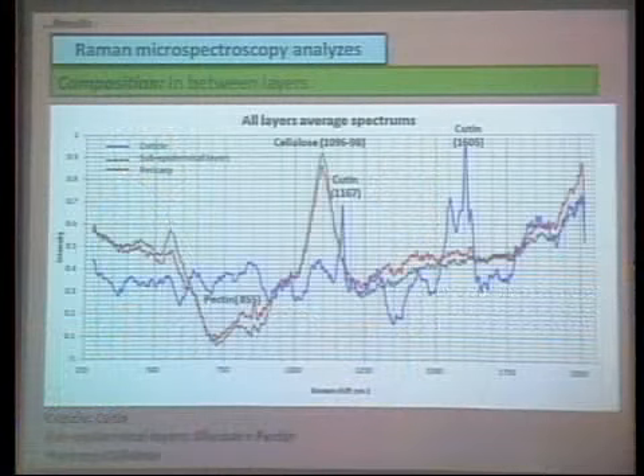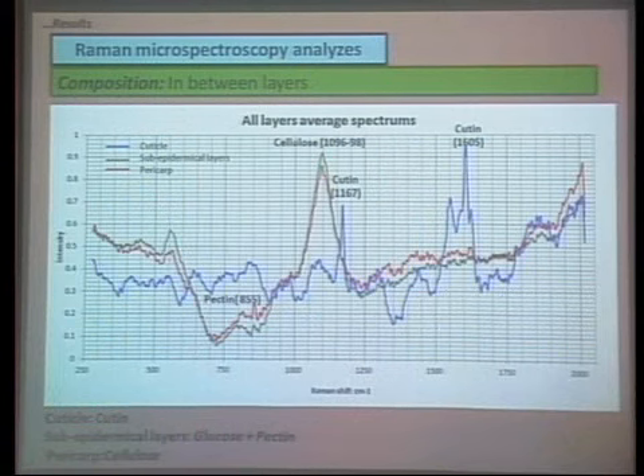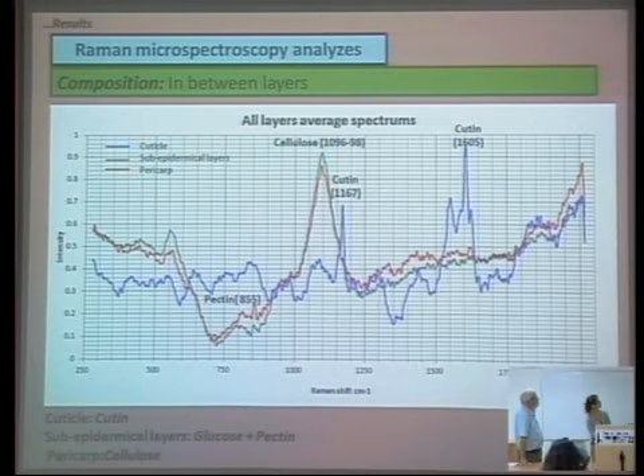But still, what are the differences between the treatments in this respect? You say that you saw the same peaks, however, does the peak represent the quantity or only the quality, namely identifying what compound is there? Let's say, for example, the red will be 1.5 and the green will be 4.0, and then you have this difference here, this delta, in intensity. If you decide that the peak length is the same, you are sure that that peak is representing cellulose. Therefore, you can compare the delta in terms of intensity for cellulose.